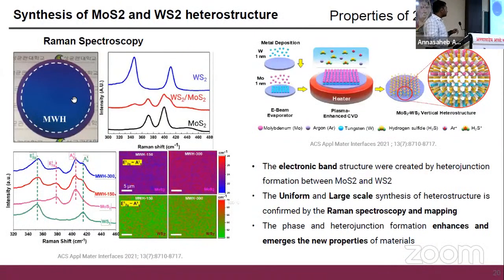We also synthesized the heterostructure, like the vertical heterostructure of these TMDC materials, and we initially confirmed it using Raman spectroscopy. In the Raman spectra, as you can see here, the presence of all 4 peaks for WS2 and MoS2 will be there.